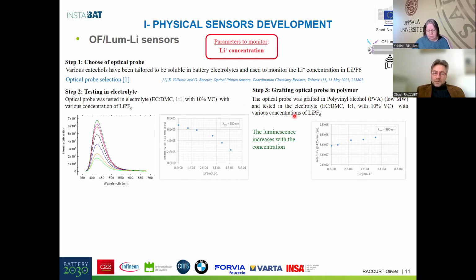The intermediate step is to check if the probe works well after the grafting to the polymer. And you can see here the result of the same experiment. We monitor the variation of the signal as a function of the concentration with this probe, but with PVA functionalization. And in this case, there is an increase of the signal, not a decrease.